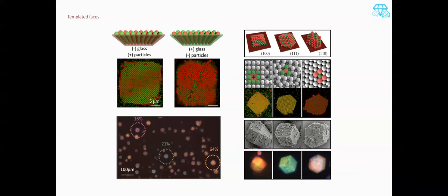And after a little bit of speculation and experimentation, we kind of figured out exactly what was going on, which is that the 100 plane was templating that square shape and growing the square pyramids that you saw in the simulation. And so it makes sense that this is the highest yield of crystal, because if you were to cut through cesium chloride in any direction you want, the highest planar density of positive particles is through the 100, so we get the square packing that's, we can't get any more positive than that. And so it's just simply presenting the most positivity to the glass as it can. And so then we ask, well, why are they all yellow? Well, it's actually kind of obvious if you think about it, the crystal is going to scatter light in an orientationally dependent manner, and they all have the same orientation. And so now if I template a different face, I'm growing the same crystal, but at a different orientation. And so I go from a 100 to a 111. And so the 111 plane looks like this. Again, this is the second highest planar density of positive particles that templates this hexagonal plane. And then it grows up as sort of a three-sided pyramid. And so those have a different orientation than the square pyramids. And so instead of being yellow, they're green. And finally, the least, the lowest yield of crystal we see is templated by the 110, which is the bulk face. And they sort of look like truncated rhombic and they come out pink.